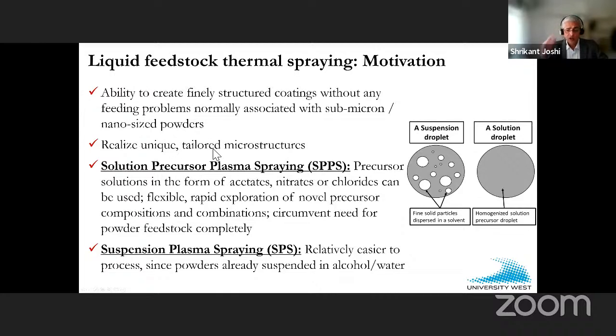So there are two ways to do it. The simpler of the two options is to put these fine powders into a suspension using an appropriate liquid medium. The more difficult approach, of course, is to not use a powder at all, but use a suitable salt solution, which will hopefully form the material of interest in situ, right? And examples of these kind of salt solutions are typically acetates or nitrates.